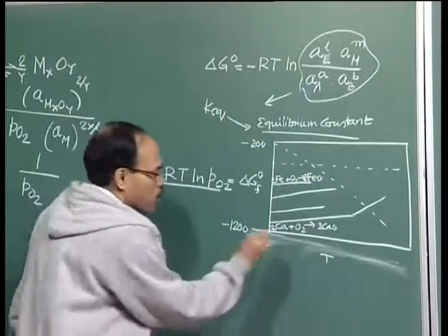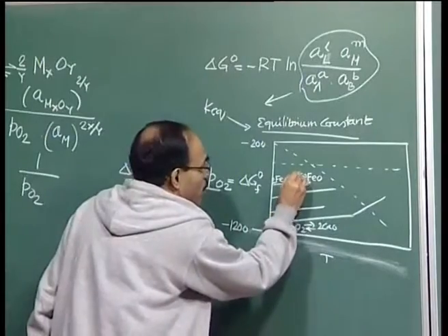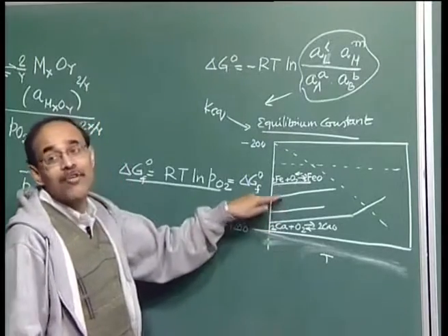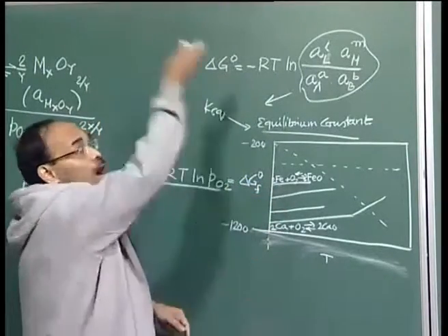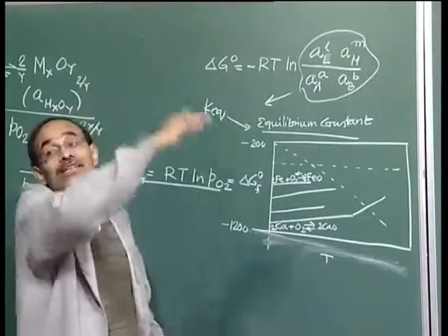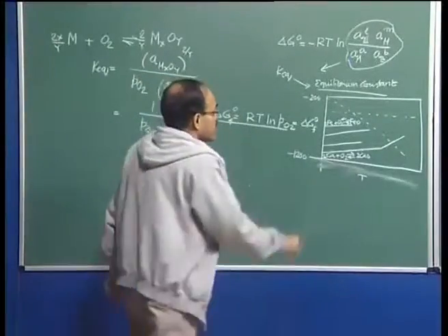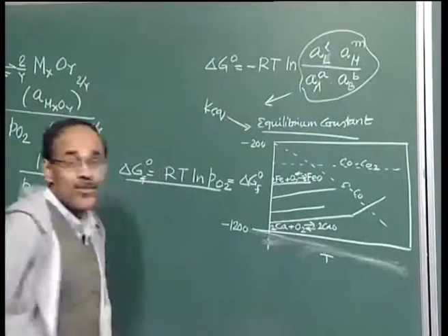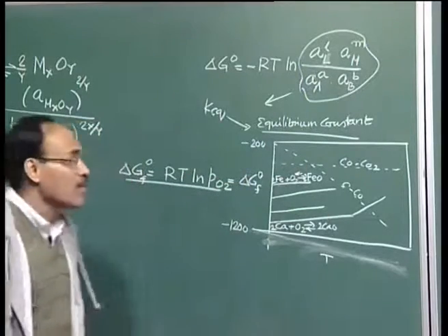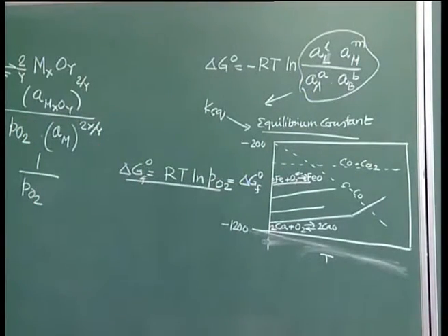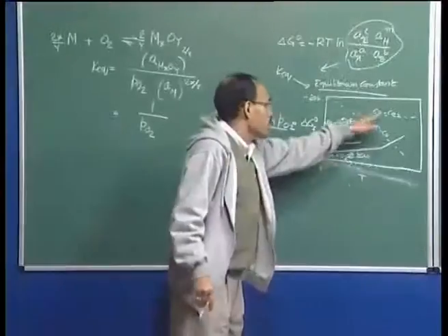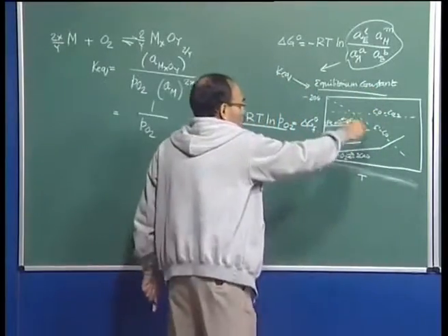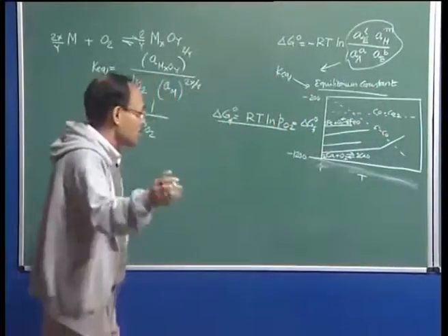So, these are all at equilibrium. So, therefore, I should maintain, and calcium, then will come magnesium, then will come aluminum, then will come titanium, then will come silicon, and if you go up, and then you see lead oxide, tin oxide, etc., which are relatively weak oxides. And this line is the CCO line, and this is the COCO2 line. You must be knowing why the slopes of the lines are different, simply because of the difference in the entropy values for these reactions, and it is the standard entropy that causes an opposite slope for carbon monoxide and carbon dioxide lines. This you must be knowing.